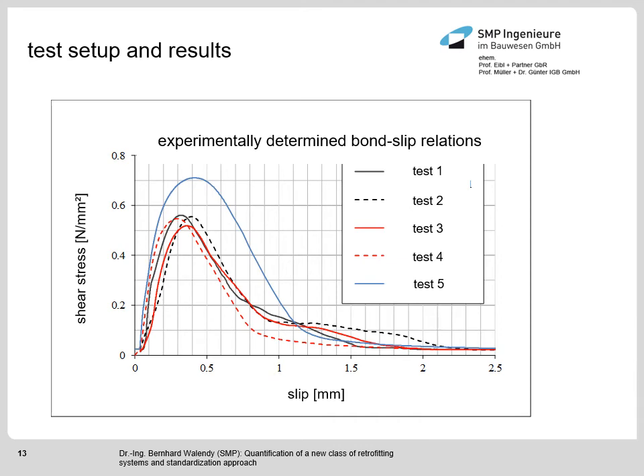These are the main outcomes from the test setup which has been shown on the slide before. These are the so-called bond-slip relations or shear stress-slip relations. As you can see here, the maximum shear stress which is transferred is around 0.5 to 0.7 Newton per square millimeter, and decoupling takes place at around a slip of 1 to 1.5 millimeter. If you are familiar with bond-slip relations for epoxy-based systems, the very soft behavior of the glue can also be seen here. And the most important thing about these bond-slip relations is, of course, to get the fracture energy, which is the integral of the curve. In this case, let me show the next slide. It's indicated like here. Let's take test number 4 as reference, and the gray surface is the fracture energy.